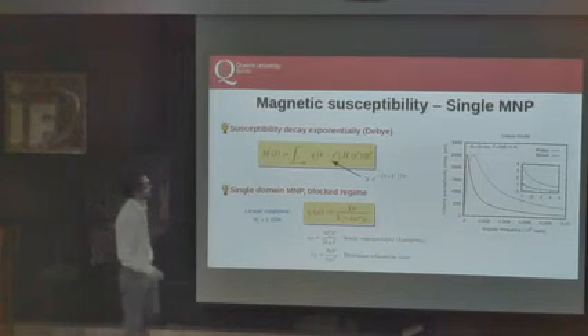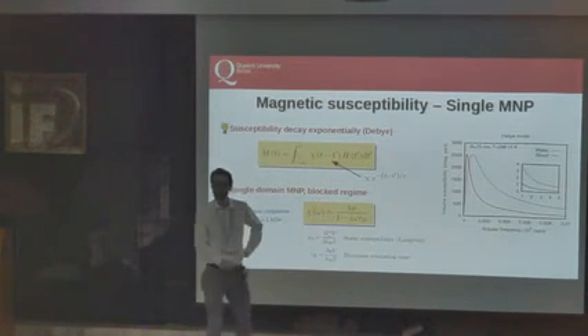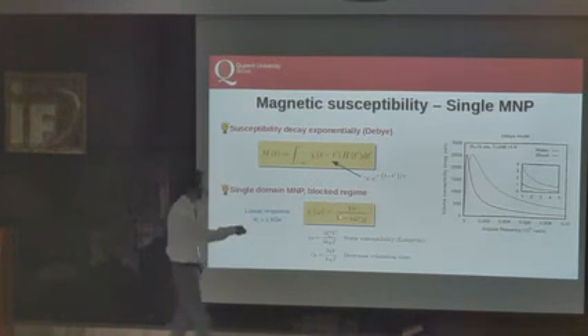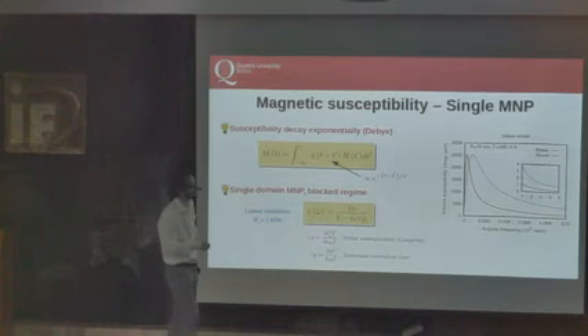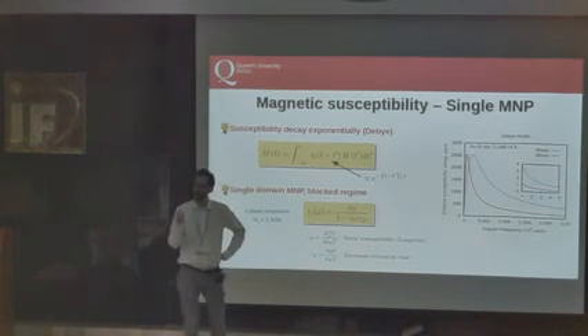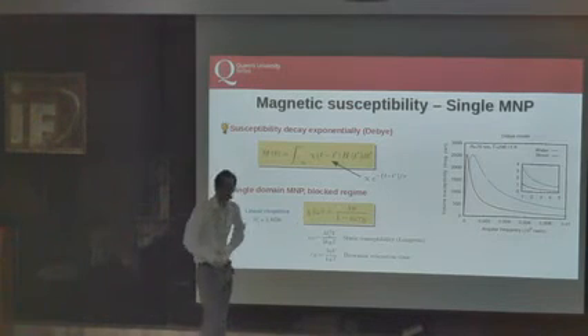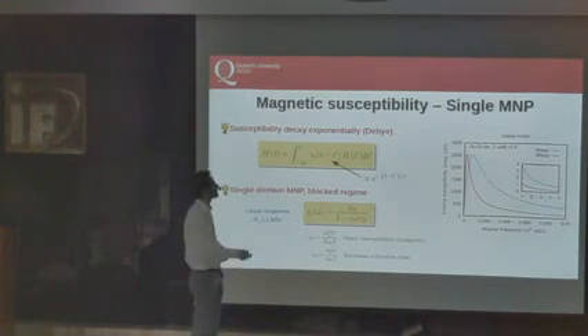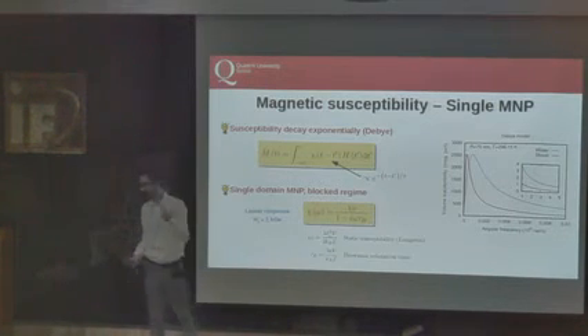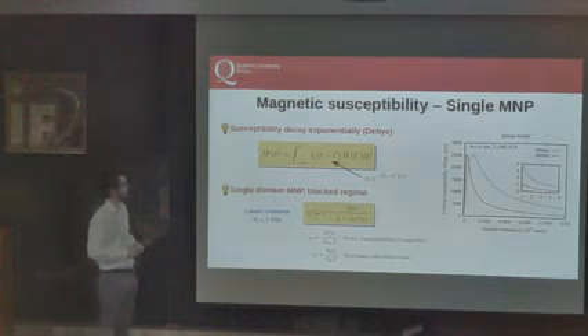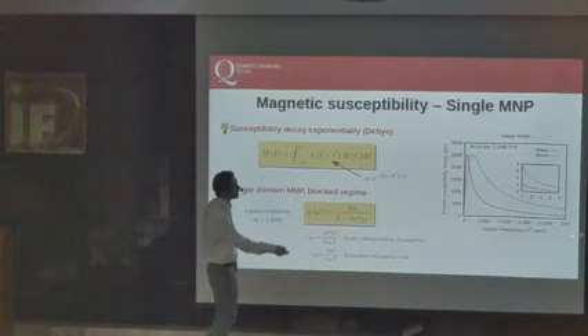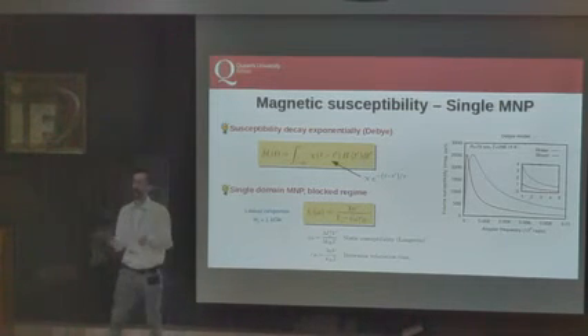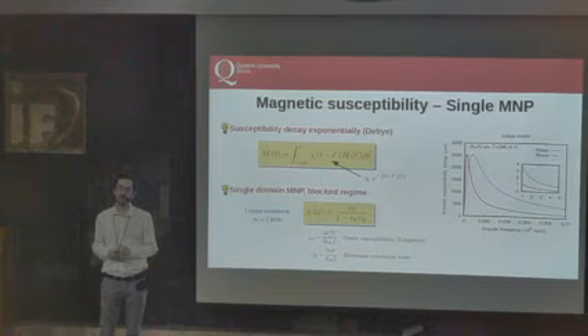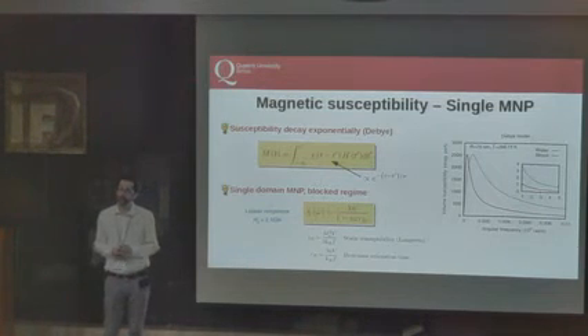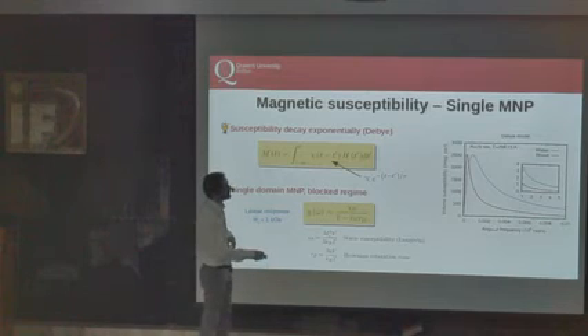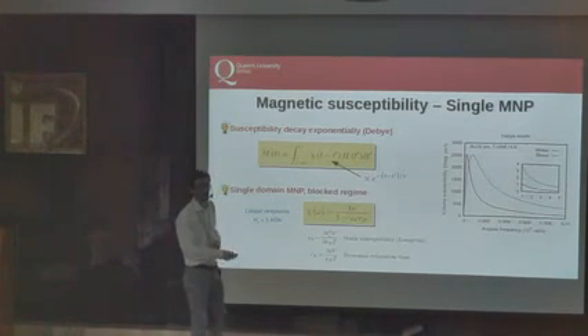Just to provide a little bit of graphical explanation of this form, the Brownian susceptibility, I used, let me say, experimental values. So radius about 75 nanometers, so this is a large nanoparticle. Temperature is room temperature. Viscosity, we usually have two cases, water and blood. And here is the angular frequency. With respect to the frequency in hertz, you have to multiply it by 2 pi. So this is probably frequency of kilohertz, probably slower.